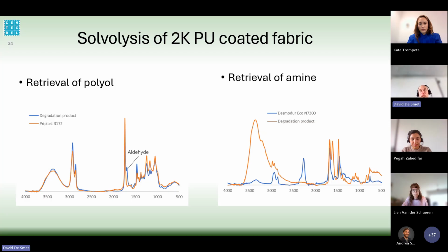So during the chemical recycling process, the polyol is formed, but a part of the polyol is oxidized into an aldehyde. This is something that we need to look further into by, for instance, changing the process conditions as well, because afterwards we try to reduce the aldehyde into the hydroxyl function again, but it was not possible to do it at 100%. So therefore we need to look back at the process conditions and, for instance, work in nitrogen, so an inert atmosphere.